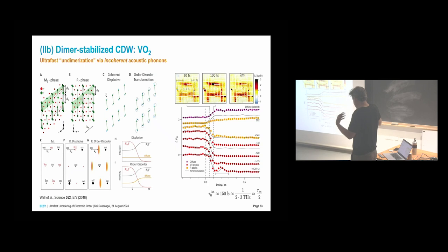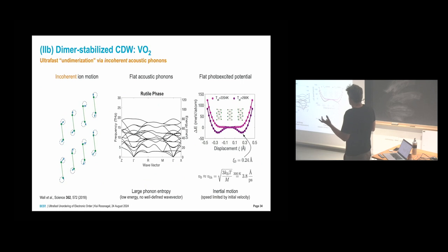So this is a little bit different from this multi-phonon phason disordering. This is due to two things. For one, you have the very flat acoustic phonon dispersion here, low energy modes in an extended region of the Brillouin zone. So this will give you large entropy. You're susceptible to phonon disorder. And then you have this flat photoexcited potential where in principle the frequency, which is related to the curvature, would be very low. But here, you do not have this coherent displacive excitation. Here, you would start out with inertial motion.